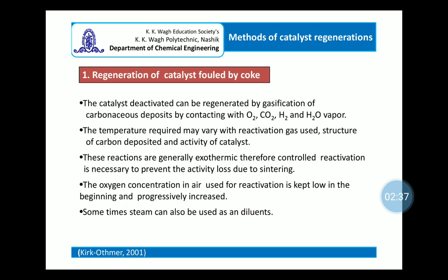The first is regeneration of catalyst fouled by coke. The catalyst deactivated because of fouling can be regenerated by gasification of the carbonaceous deposit by contacting it with oxygen, carbon dioxide, hydrogen and water vapor. However, the temperature required may vary depending upon what kind of gas we are using for the reactivation, the structure of the carbon deposited and the activity of the catalyst.